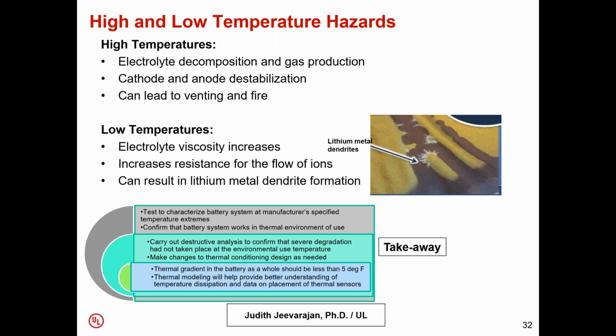When we look at low temperatures, again, this depends on what the manufacturer specifies as the low temperature that the cell can work at. If you go below that, the electrolyte viscosity usually increases, and this increases the resistance for the flow of ions, which can then result in lithium metal dendrite formation, because the lithium ions have difficulty intercalating within the anode electrode. And so the best thing is to characterize them at the manufacturer's specified extreme temperatures and confirm that they work in the environment that you want them to work.